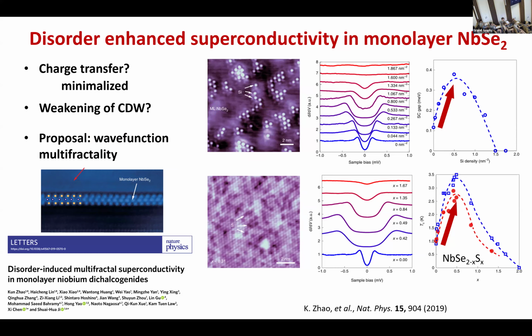I think they still cannot really fully answer the problem. It could be that these dopants, although they do not transfer charge, can destroy the CDW. So by destroying the charge density wave, you could enhance TC, enhance the superconductivity, because if we assume superconductivity and charge density wave are competing with each other, you suppress one, you may enhance the other one. So this could be a real effect. However, this cannot explain why people before observed that when you transfer charges to the system, both the charge density wave and the superconductivity get enhanced. So I think there's still something ongoing with this. But the take-home message here is that MBE grown samples could be interesting, maybe compared to the exfoliated ones.